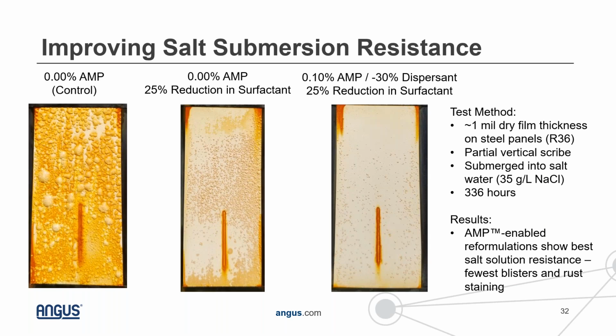The other interesting aspects that we see as a result of this is that we did some salt submersion resistance testing. So this was testing where we essentially applied the coating onto a steel panel, just like we would for the B117 corrosion test. But instead of using a salt spray, we simply submerged these panels into a 35 gram per liter sodium chloride salt solution.